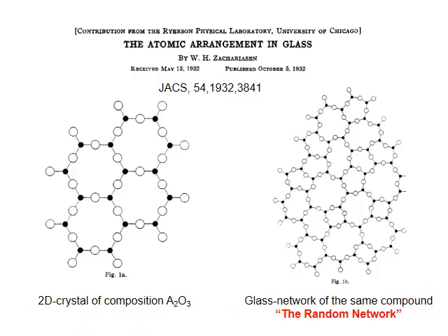As early as 1932, Zachariasen, working with the new technique developed at that time, X-ray diffraction, tried to explain the absence of diffraction patterns for some samples. He sketched a 2D scheme where, with the very same structural unit, one could construct either a 2D crystal, that is, displaying long-range order, or an amorphous sample, that is, displaying no long-range order.